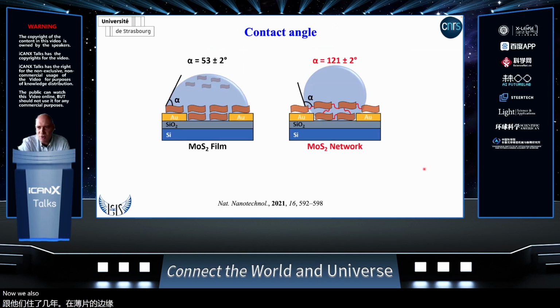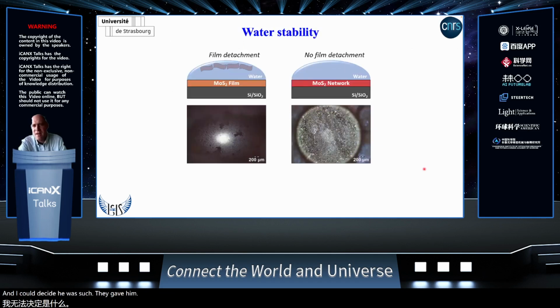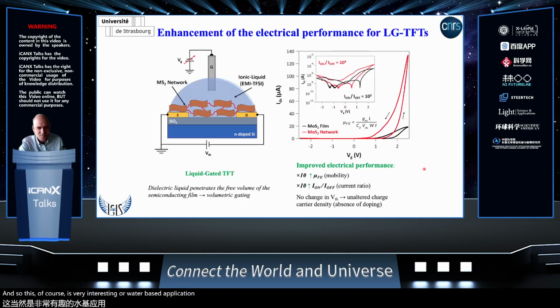Now, we also noticed that the difference between the film and the network was hydrophilicity. The film was very hydrophilic and the network was very hydrophobic. This hydrophobicity gave a much stronger stability, or robustness, of the network underwater, with no detachment. This, of course, is very interesting for water-based applications. Of course, we are also interested in exploring the electrical properties when integrated inside a real device.